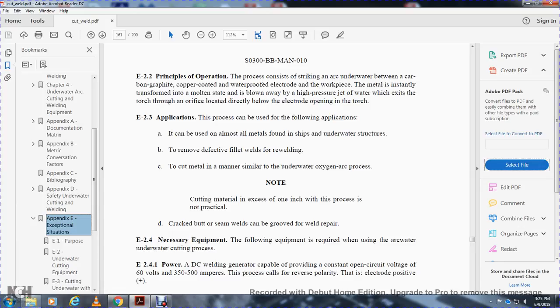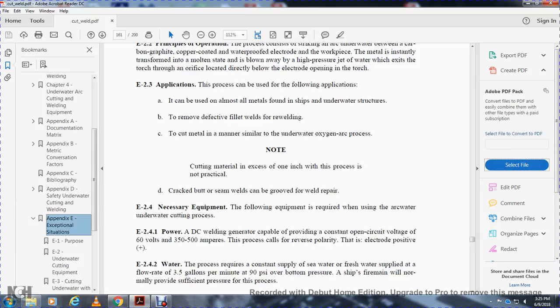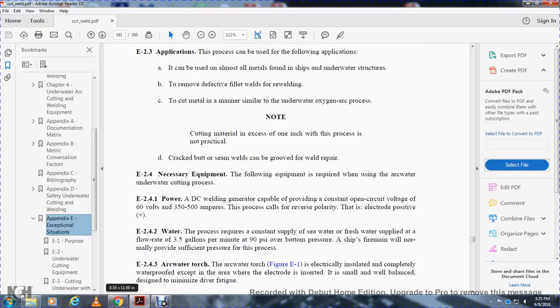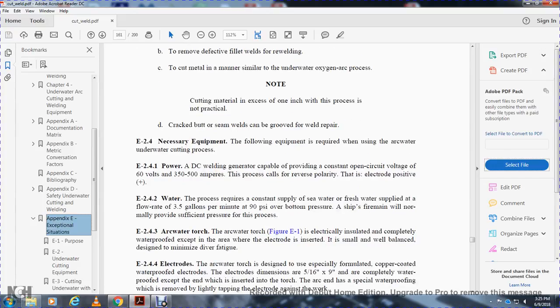E2.4, necessary equipment. The following equipment is required to be used in the arc water underwater cutting process. Power: AC/DC, but a DC welding generator capable of delivering a constant open circuit voltage of 60 volts at 350 amps. This process calls for reverse polarity, electrode positive. E2.4.2, water. The process requires a constant supply of seawater or freshwater supplied at a flow rate of 3.5 gallons per minute at 90 psi over the bottom pressure. Ship firemain will normally provide sufficient pressure for the process.